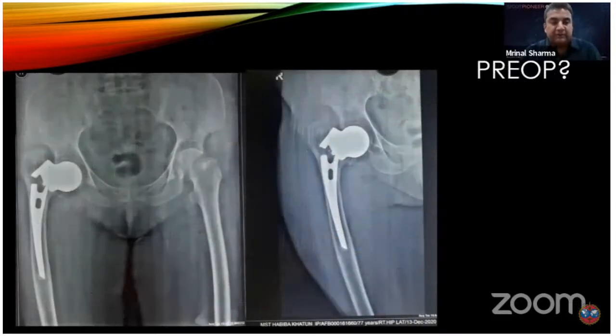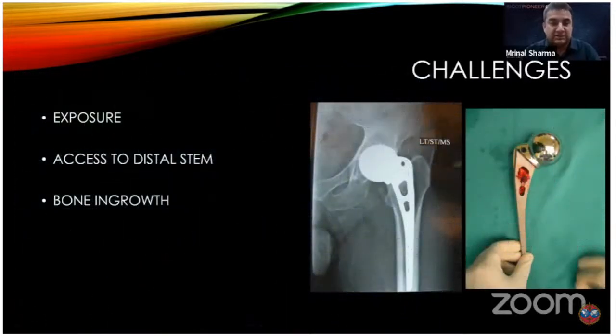So these are her preoperative x-rays. You can see a Thompson prosthesis which has been broken at the junction. The distal stem seems to be well fixed, and this is usually the case in such a scenario. You have difficulty in exposure, you have difficulty in access to the distal stem, and there is bone ingrowth. You can see this is another case which I had revised for a Thompson prosthesis where the bone ingrows into these cavities in the stem itself, and it's very difficult to access these. If the collar is intact, it's even more difficult.